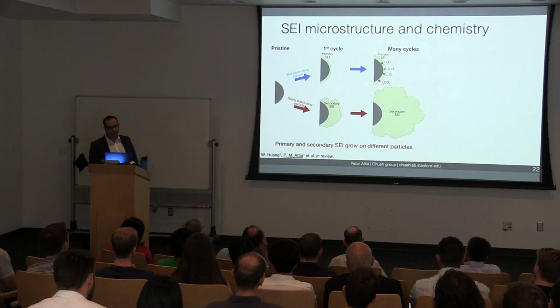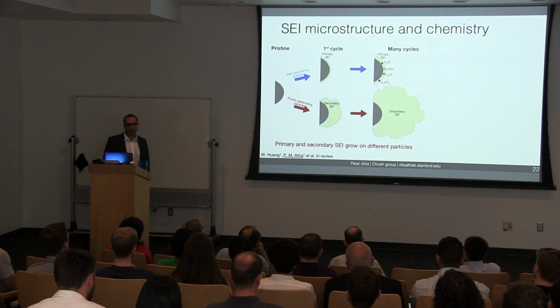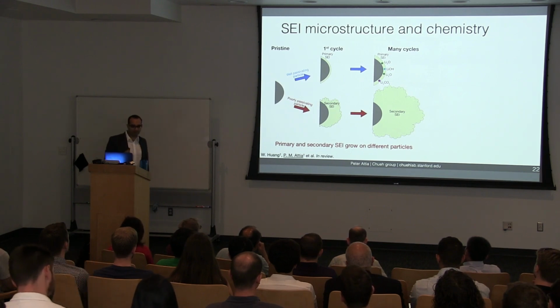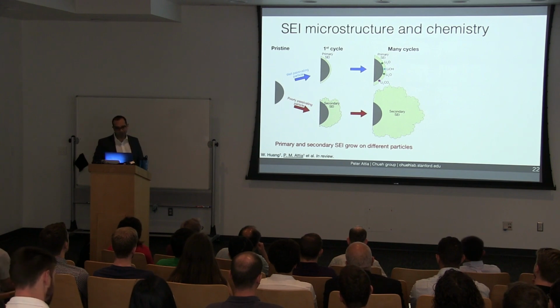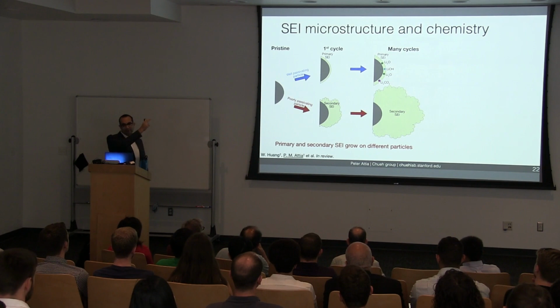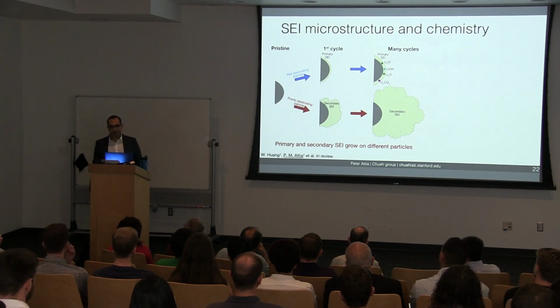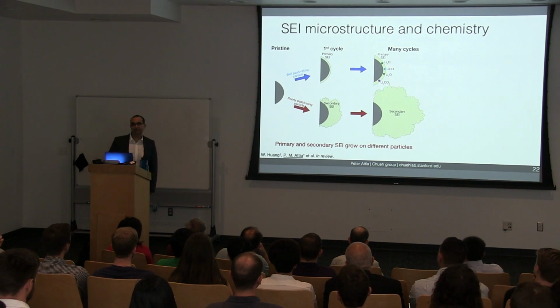The fact that it's so thick means that it consumed a lot of lithium, which is bad news for battery capacity. Secondary SEI could also be a big problem for real batteries, since it blocks lithium-ion transport throughout the electrode. This reduces the rate capability, which affects things like fast charging. Now, one open question is what causes some particles to go primary SEI and others to go secondary SEI. If we can figure this out, hopefully we can design battery particles to go primary SEI instead of secondary SEI.